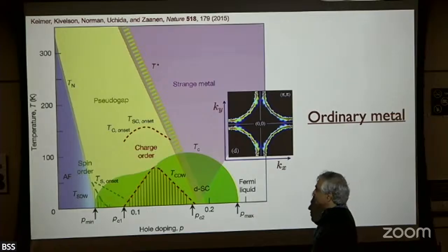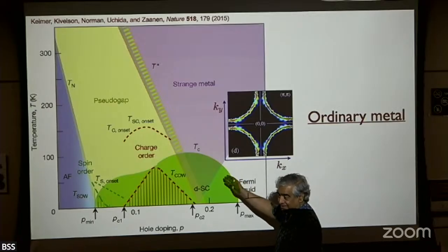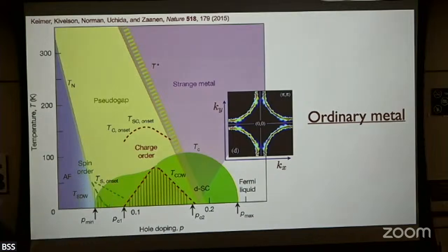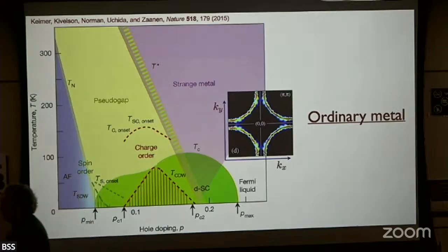Well, there are measurements of the paramagnon in neutron scattering, and they clearly see antiferromagnetic dominance. But what they see is actually very, very broad. So in fact, the interpretation in our favor is that what they're seeing over here, these very broad but intense paramagnons, is really the signal of these spin-half excitations.